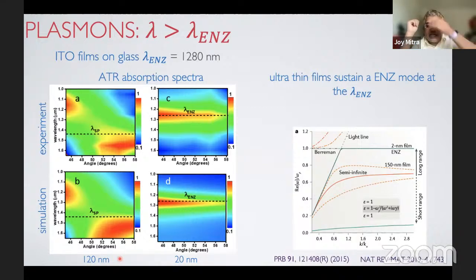But what was even more surprising to us was that if we decrease the thickness of the film, if we take the same tuned films, but much, much thinner, 20 nanometer thin films, then the plasmon absorption spectra was very, very different. Instead of having this asymptotic behavior, experimentally we saw that the absorption band was straddling the lambda ENZ wavelength. And when we did the simulations, indeed that turned out to be so. So we were rather intrigued: where does this come from?